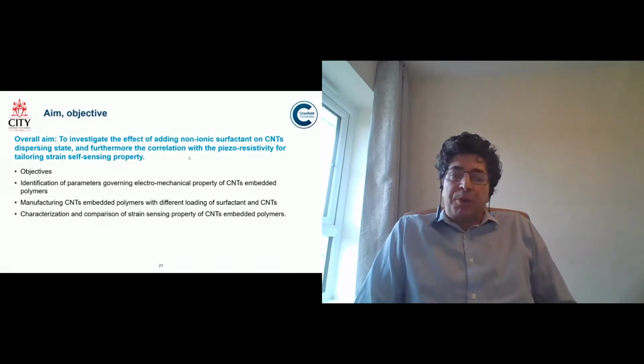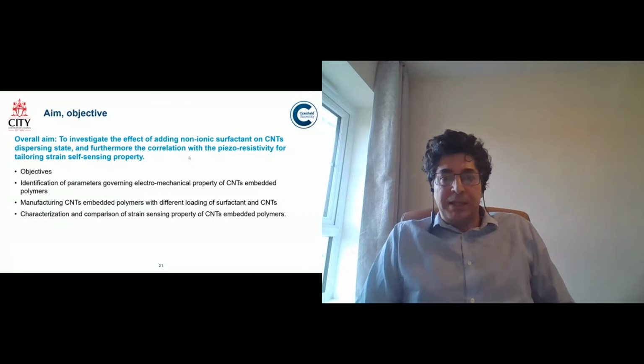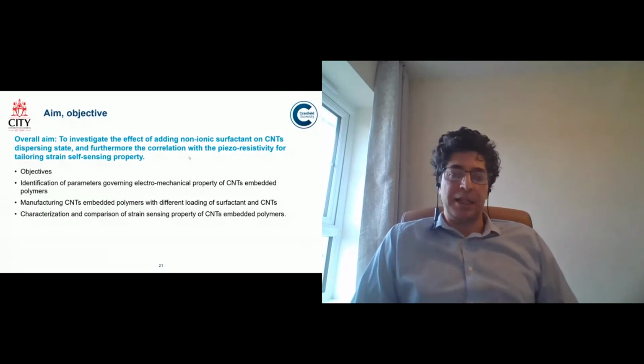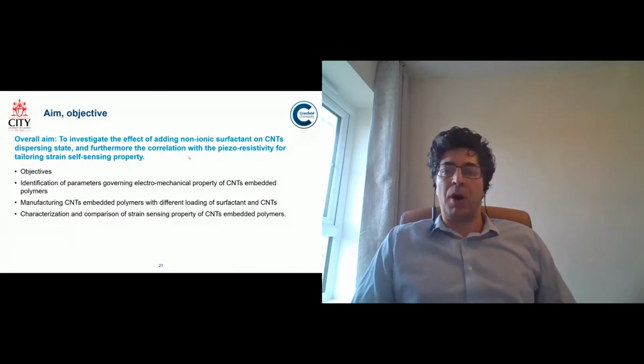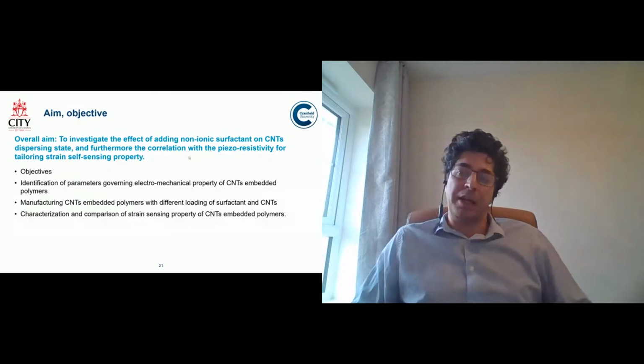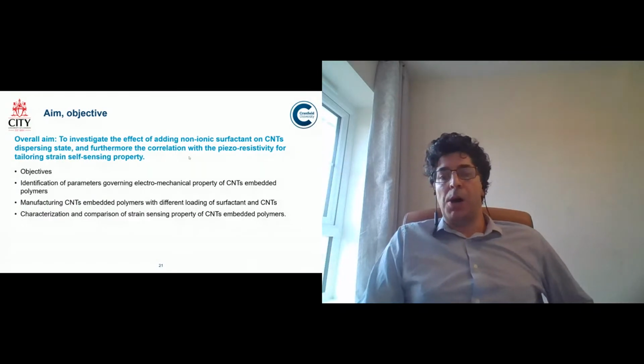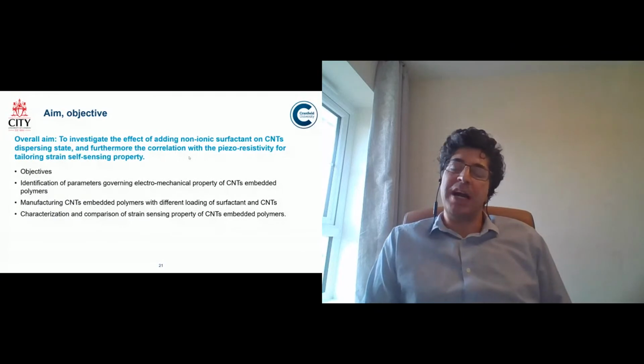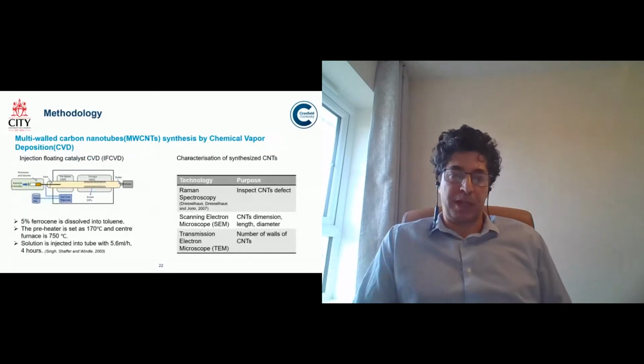So what kind of process parameters might have an effect on reliability of this smart sensing? And we said that maybe adding a surfactant would be an issue, and it is actually an issue, because we came up with mixing the carbon nanotube, ultrasonification inside a surfactant, and then mixing it with polymer, because we wanted to come up with a straightforward, in conventional saying an easy process to make a smart composite rather than a very complex process, but it's still applicable to scale up.